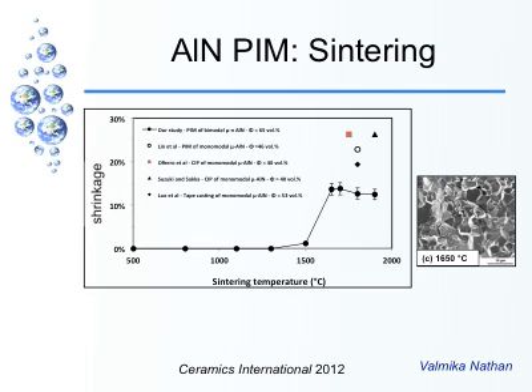Okay? Yes? While sintering with the nanoparticles, was that effective? Was there agglomeration in it? So what we found was the agglomerates could break down in the twin screw extruder when we mixed it, and that allowed us to get the very high volume fraction. We have to do additional experiments in this region to understand it, but you can see from this microstructure of the fractured surface that it is 99+% dense. There's almost no porosity over there.